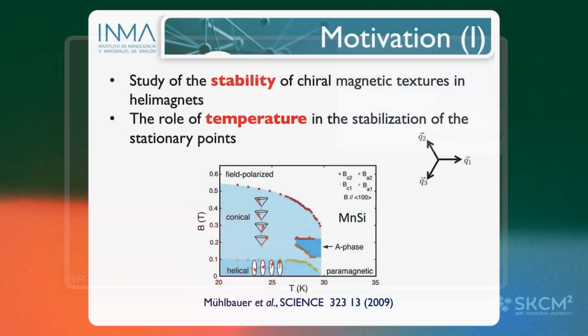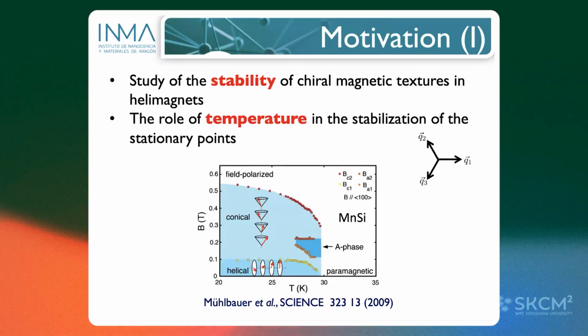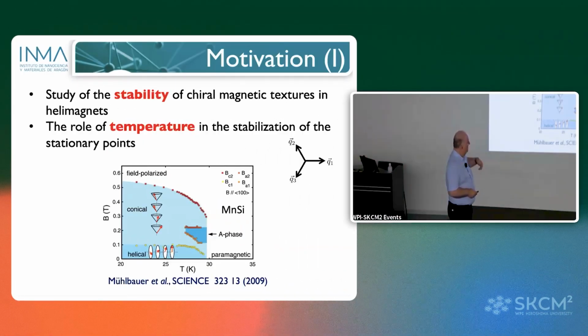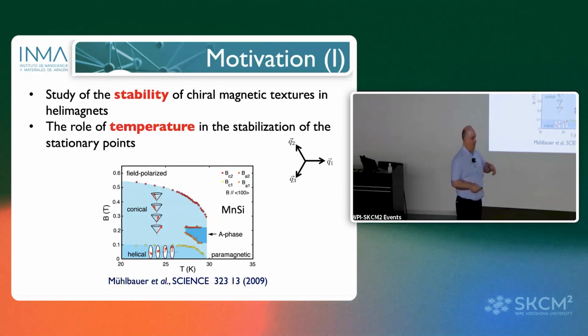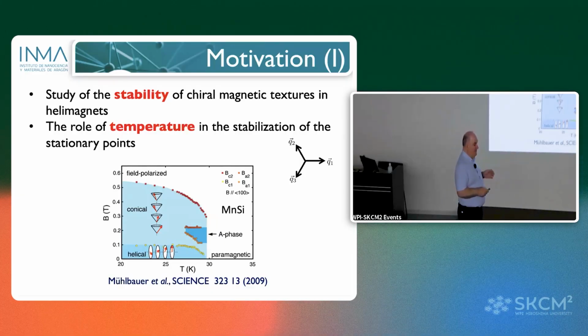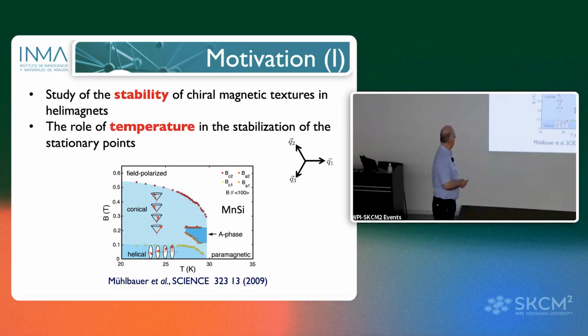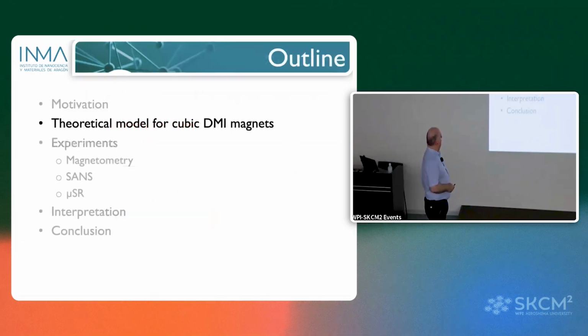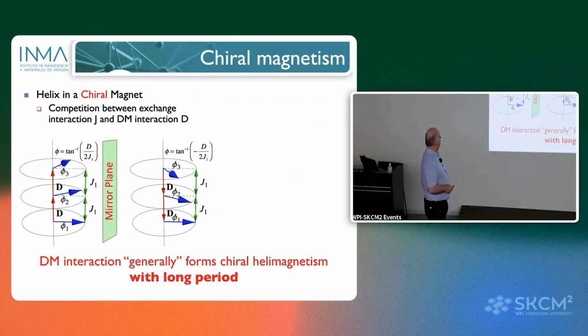And the stability, what is the stability? Even at zero temperature, the solutions of the Euler-Lagrange, the stationary points, can be unstable solutions. The derivative of the energy has a zero, but they are not stable solutions. We need to see that when you are moving a little bit the solution from the equilibrium point, you are going back to the equilibrium point. Otherwise, it's an unstable solution. If you are in a maximum of the energy and you move a little bit your solution, you will lose the state. Then let's go to see this first.